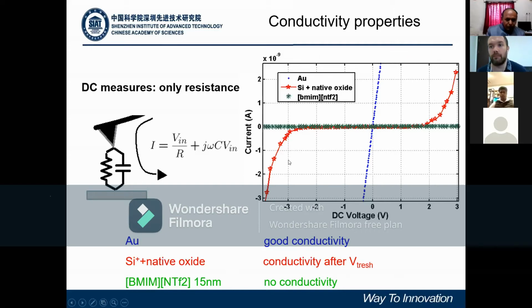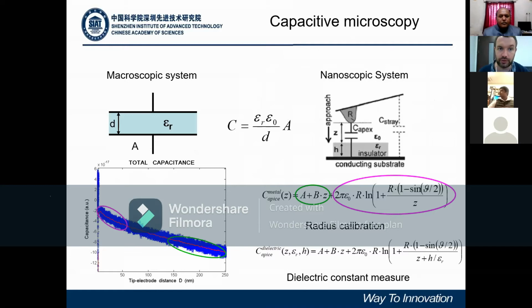Here we hypothesize that this is a dielectric film, and the AFM probe can also measure the capacitance by switching to AC mode. We can have something similar. When we have a macroscopic system, we have a capacitor, and all of you know how to measure the capacitance of a parallel plate capacitor, and from that it is possible to measure the dielectric constant. For a nanoscopic system, such as a probe with a conductive substrate, the model used is different, more complex, as you can see here.